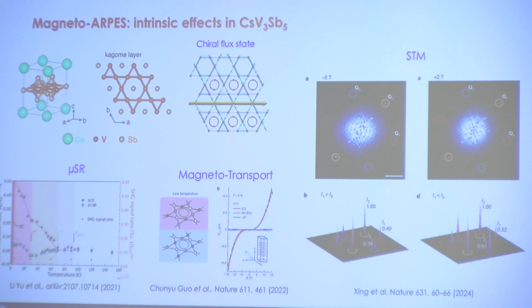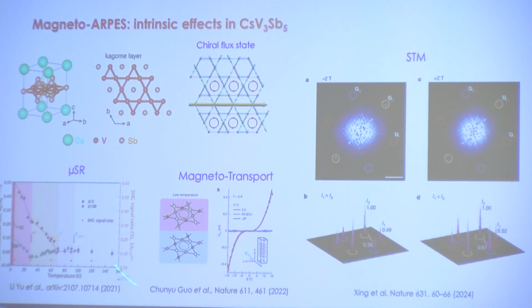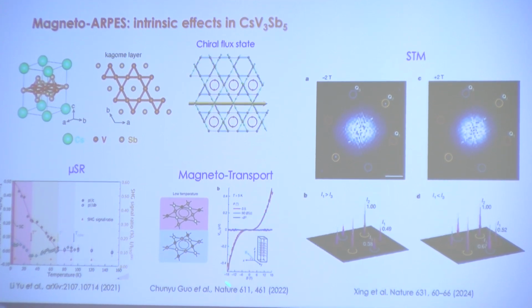For example, this is the μSR measurement that Stephen has mentioned, where you see the onset of the CDW and then a change in the relaxation rate of the muons. And then this is the magnetotransport measurement under a field, which has an odd in-field effect. And then this is, I will leave it for her. I'm happy that she will talk about this, so I won't spend too much time on this.